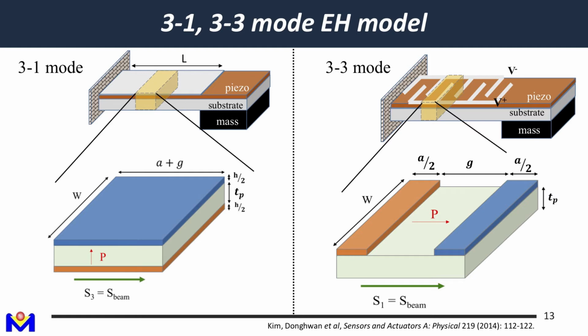But if we want to harvest in 3-3 mode, then we need to have a so-called interdigit electrode. So the electric field will also be in this direction, that will be in parallel to the beam axis. So we can harvest with 3-3 mode. And like I just mentioned, the D33 piezoelectric constant is in general larger than in 3-1 mode.